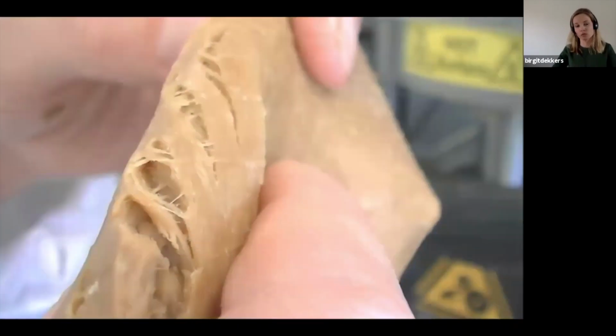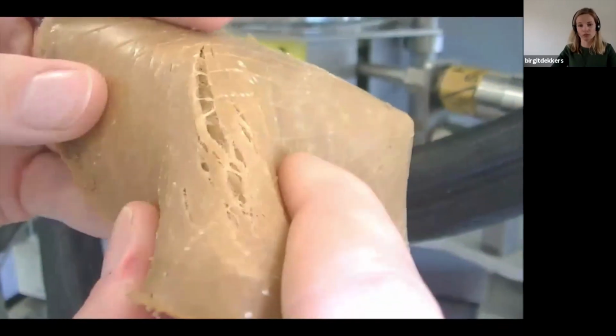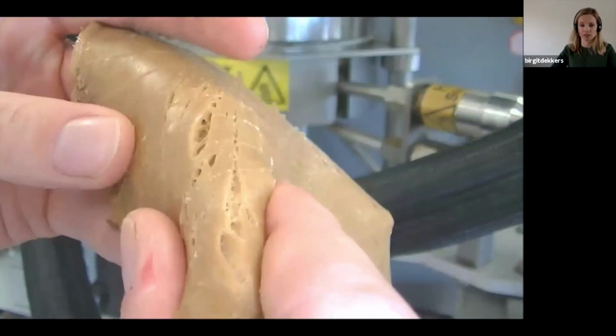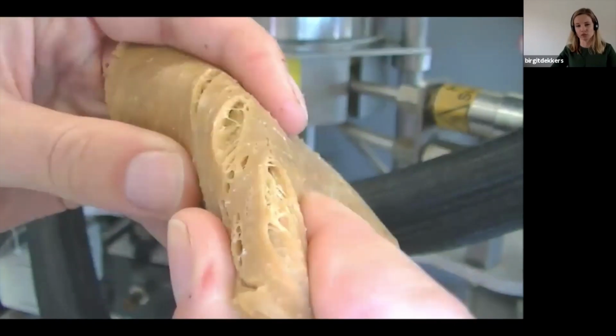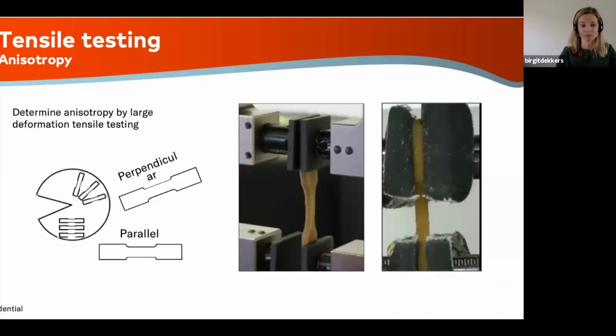Often what we do is we fold these types of materials and look at the structure. And what you can see then is how the fibers start appearing. And this is a device of 100 grams where we do most of our early stage research on. 100 gram is enough to look at the types of structure. You can vary the time, the temperature, and the shear rate. And it's a great research device.